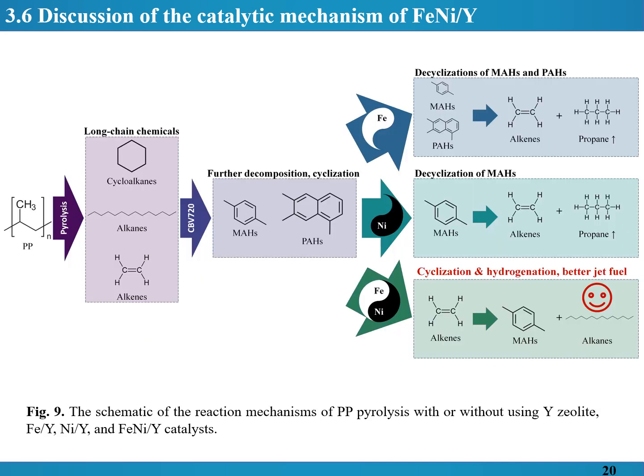Figure 9 shows the reaction mechanisms of PP pyrolysis with or without using Y zeolite: undoped Y zeolite, nickel-doped Y zeolite, and both iron and nickel-doped Y zeolite catalysts. Without a catalyst, pyrolysis can reach up to 86 weight% wax, which contains long-chain cycloalkanes, alkenes, and alkanes. With the addition of Y zeolite, the Y zeolite further decomposes long-chain hydrocarbons into short-chain hydrocarbons and promotes the formation of monoaromatic hydrocarbons and